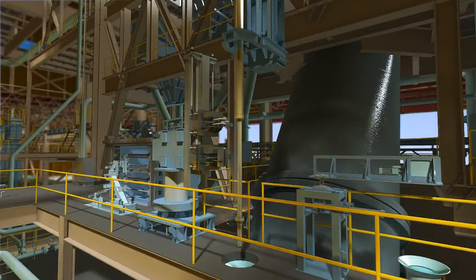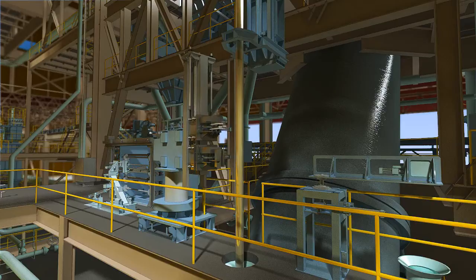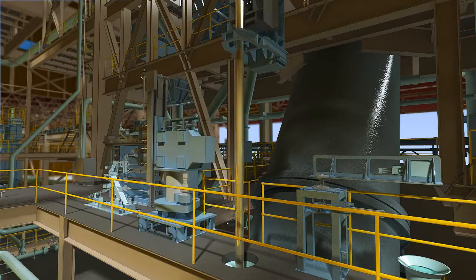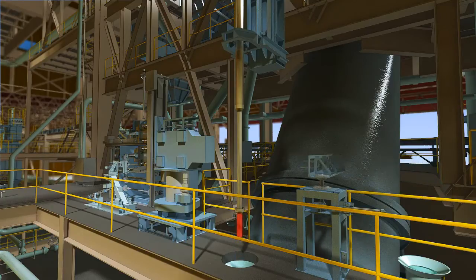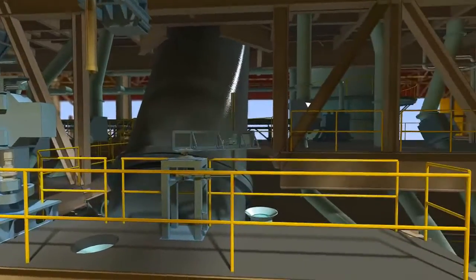The probe installed at the tip of the sublance is used to check the end component and temperature of the molten steel and to check whether it reached the target temperature and oxygen. If it reached the target value, it will proceed with tapping. If it doesn't, blowing is repeated until the target value is achieved and the blowing process is stopped.